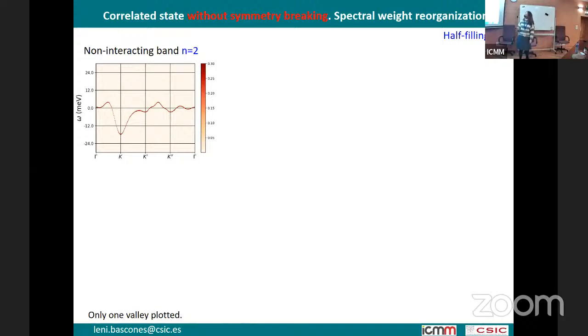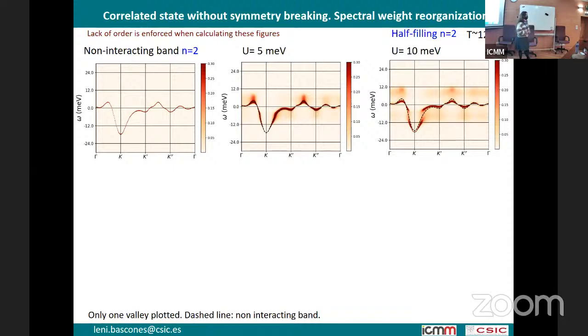So let me first introduce U, which is not very large. You can see the effect, and what is happening to this band. There are two things happening. Our band is changing shape, so it's becoming a bit renormalized. You can compare in this plot: the dashed line is the non-interacting band, and what we see in red is the spectral weight. This band starts changing a bit, but at the same time it's becoming broadened. And there is a reshuffling of the spectral weight. You can see how we are sending spectral weight to higher energies.